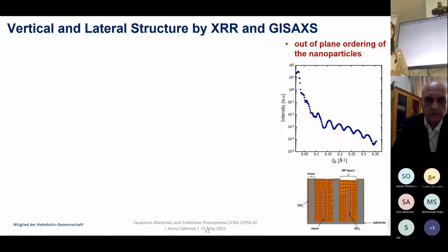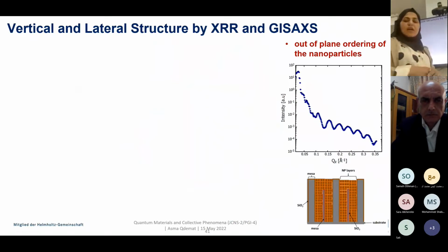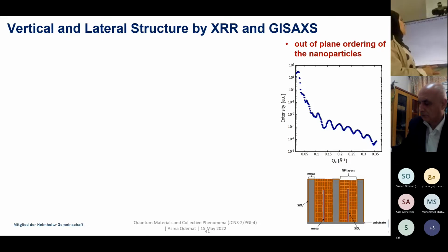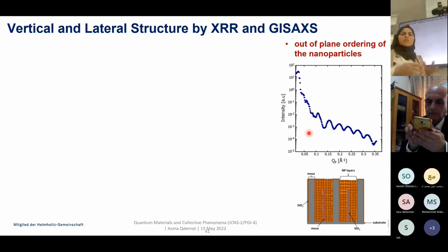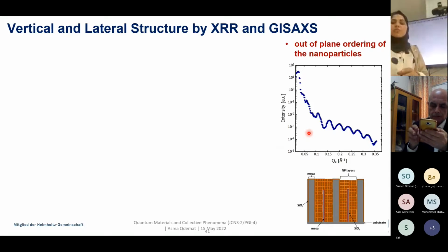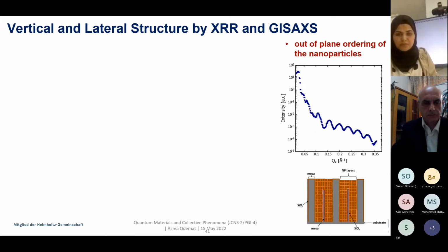Now, after I characterize the nanoparticle and the grating lines of the silicon wafer, I try to combine both together in order to obtain a single crystalline 3D arrangement of nanoparticles. For this, I use a dip coating preparation method. To study the nanoparticle arrangement that I obtained, I performed X-ray reflectometry measurement, as we can see here, in order to see the out-of-plane ordering of the nanoparticles, which shows some oscillation due to the nanoparticle layer inside this groove.